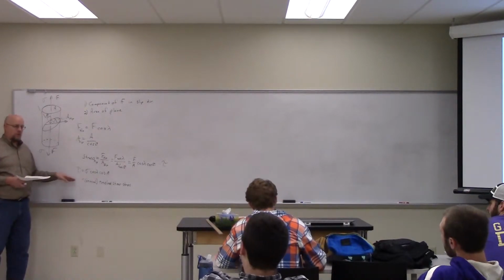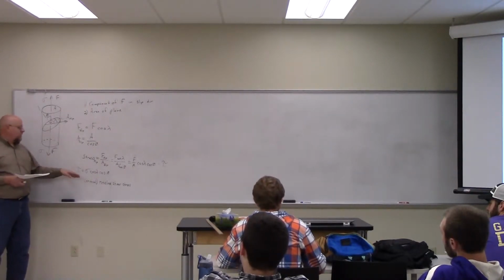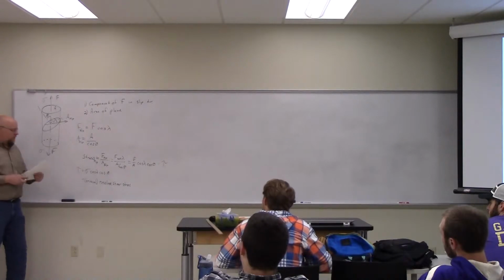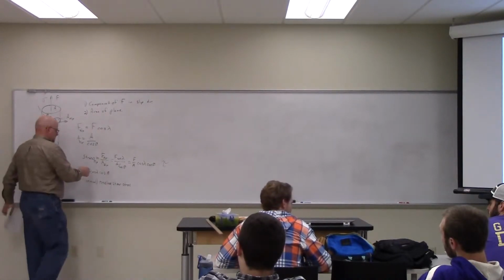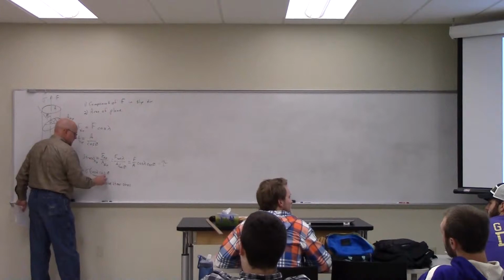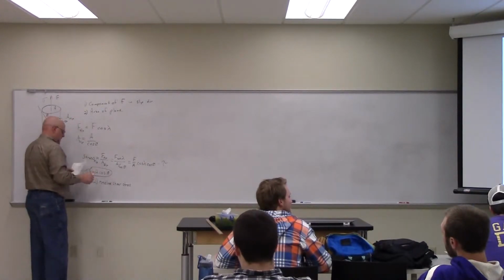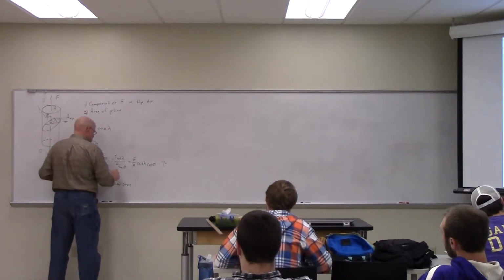Okay, so in a single crystal. So this resolved shear stress, and if it's the maximum one, it's the critical resolved shear stress. And then this multiplier here, the 2 cosines, is called the Schmid factor.